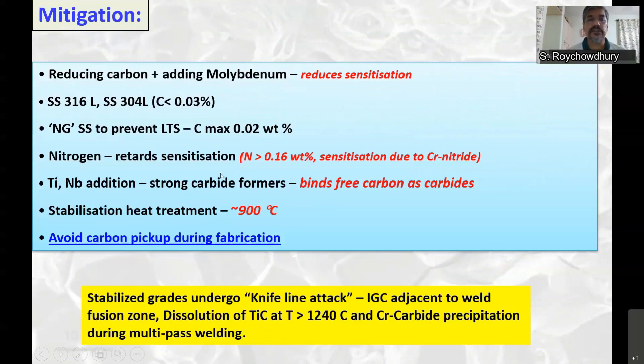Addition of nitrogen not only retards sensitization, but it also brings up the strength level of the stainless steel, because by removing carbon, you sacrifice the strength. But you cannot have too much nitrogen, because if it is in excess of 0.16%, then again chromium nitride will precipitate and sensitization can occur. Addition of elements such as titanium and niobium, they are strong carbide formers in excess of 900 degrees centigrade. If you give this stabilization heat treatment, then titanium and niobium carbides form. So subsequently, no free carbon is available for chromium carbide precipitation and sensitization.